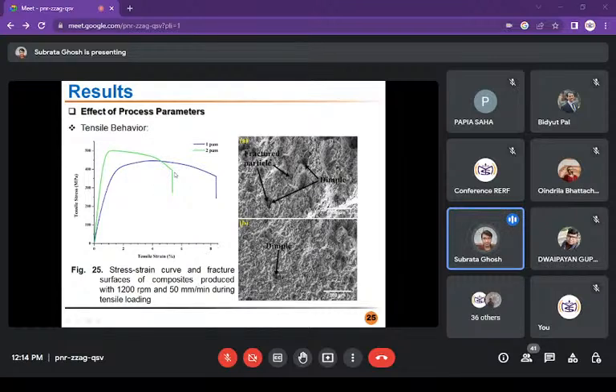Just see, we have processed the material and it is showing fully ductile nature. Similar to ductility, yield strength is also very much improved. The blue line is for the first pass, and the other line is the second pass. If you compare the first and second pass, it is easily visible that the overall yield strength and other properties are improved for the second pass because the overall distribution is good. If you look at the fractured surface under the SEM, you can see a lot of dimples and fractured particles. This is basically ductile fracture happening in tensile failure.